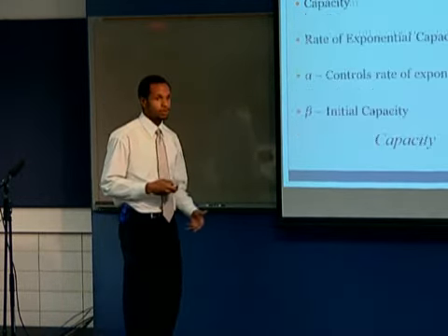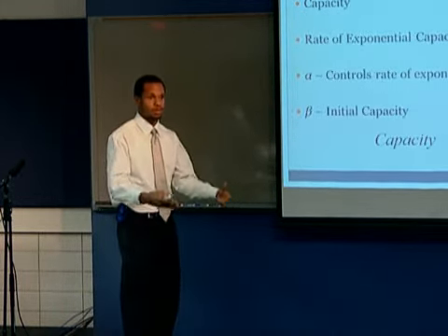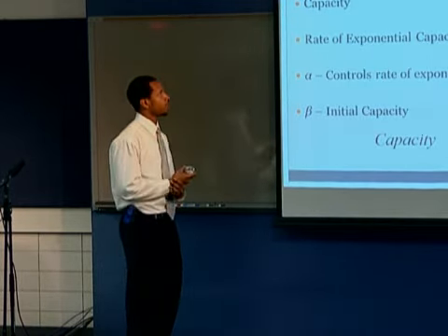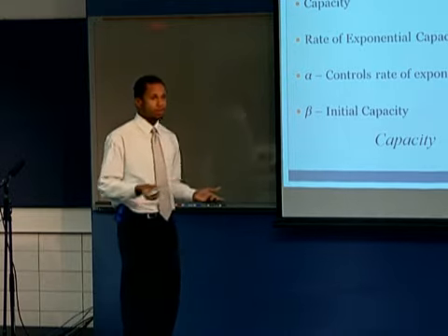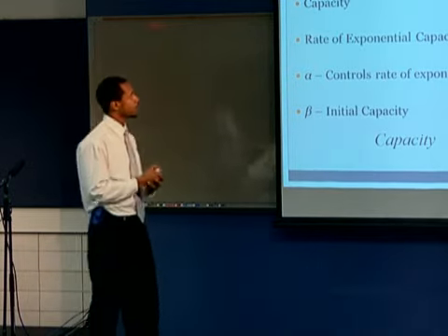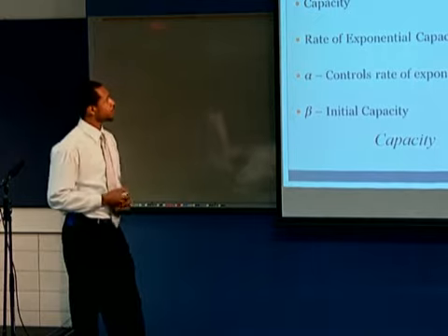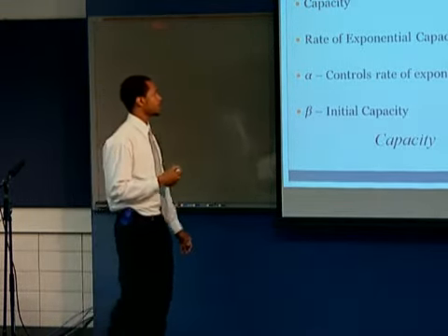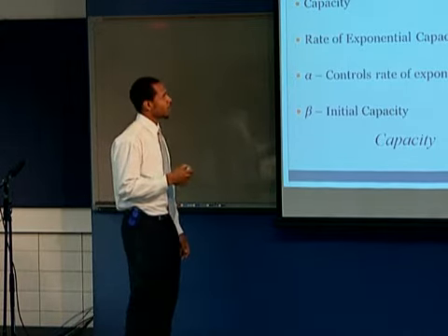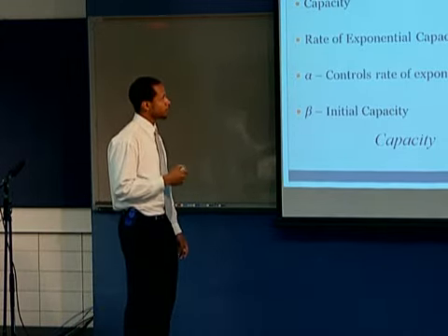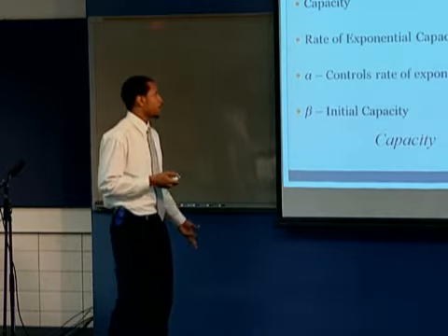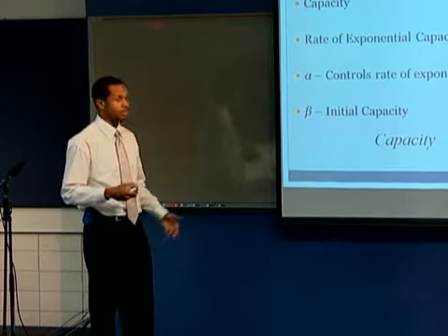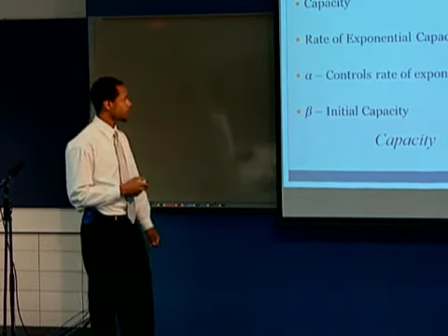And so after each filtration, I propagate the particles, and that propagation is what's used to predict the remaining useful life of a battery. Now, what are the properties of these particles? The properties of these particles are listed as these parameters. The first one is, self-explanatory, the capacity. And the second one is a rate of exponential capacity fade. Through experiments, I found that by modeling the capacity to fade exponentially, I actually get better predictions than anything else I've tried to implement so far.